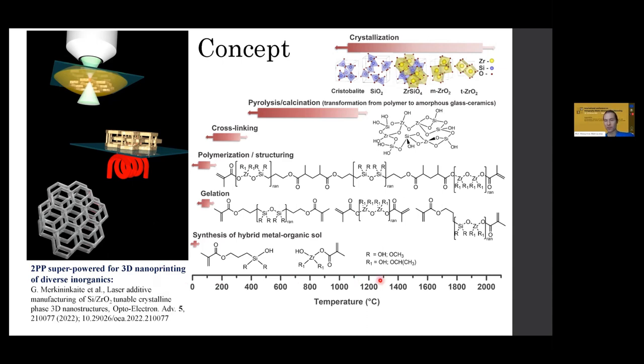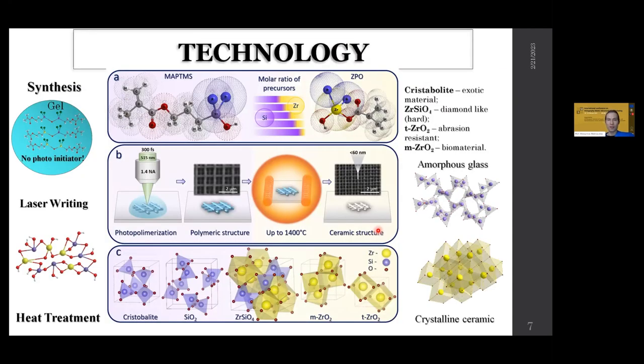Just to have an imagination of the temperature scale, the polymerization and all the material preparation works at room or near room temperatures. We heat it at higher temperatures, exceeding 140 or 150 degrees, we start cross-linking of all possible carbon bonds. And eventually, if we apply higher temperatures, we start to evaporate the smaller organic compounds. We start to break them, depolymerize, and eventually all the organics are removed. And finally, we will result in some inorganic substance, which will depend on the initial ingredients of our hybrid resin. So we can expect to achieve crystallized silicon dioxide, monoclinic or tetragonal zirconia as a final product if we use SZ2080 material.